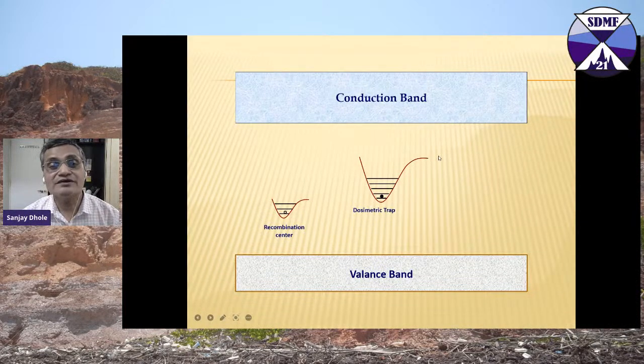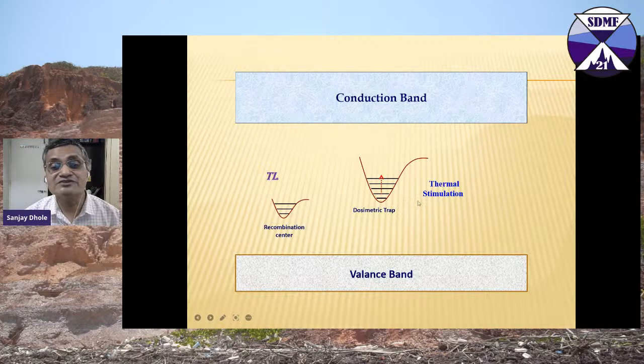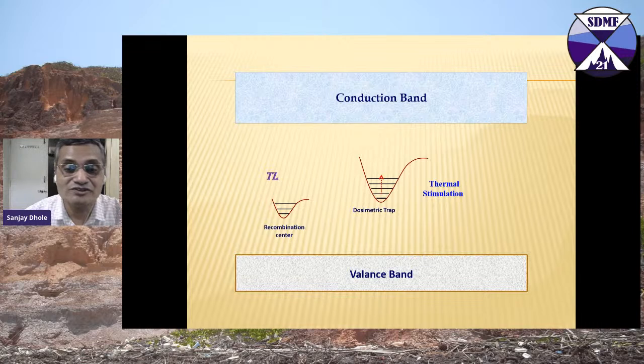So this is the stimulation. The electron goes into the conduction band, and from there into the recombination center, and then you have the radiation coming off. That is called thermal stimulation. When you increase the temperature to more than 300 degrees Kelvin, the energy of the electron is more than 0.025 electron volt, and they make the transition from this level to the conduction band. They stay for some time here and go into the recombination center, and while going into the recombination center, this gives off the photon. This is what is called the TL recombination.